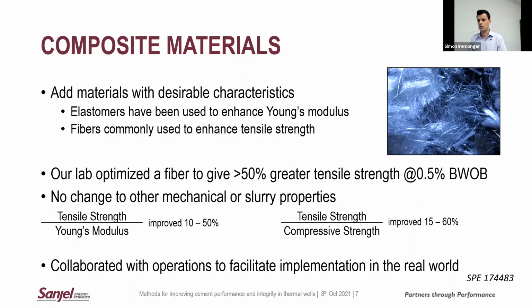Fibers offer one potential advantage because they have substantially higher tensile strength than cement, often orders of magnitude higher, so you can get away with adding very low loadings and get substantial enhancements in tensile strength. To give some examples, I've included the references to the relevant SPE papers we've previously published in the bottom right-hand corners there. We were able to enhance tensile strength by more than 50% in a conventional thermal cement blend by adding only 0.5% by weight of blend.